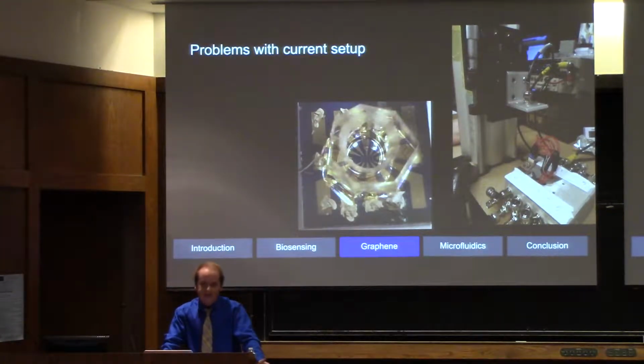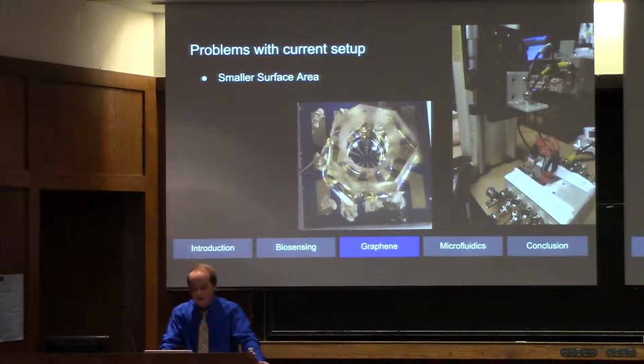Unfortunately, our current method of testing devices limits us in several ways. The main problem with this method is that the probability of the molecules actually interacting with the graphene is relatively low. The graphene has a very small surface area relative to the rest of the chip, which means that there is a very small surface area where they're actually interacting with the biomolecules. This limits the probability that they're actually going to be attaching.